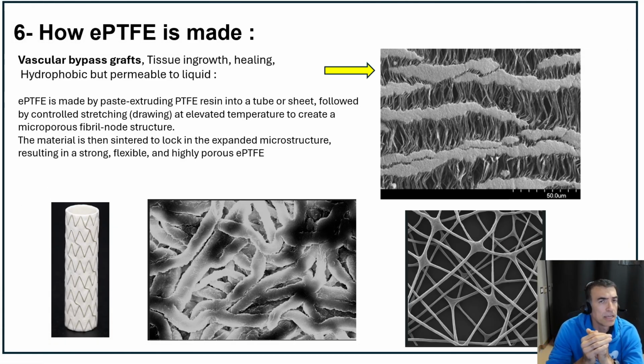We explained that PTFE is sensitive to orientation. It's highly crystalline, and because of that property, when PTFE is stretched, those crystalline structures can create an island shape, and then with further stretching, a structure is formed called fibrillar structure with a crystal lamella in between, and this would create a porous structure that would make the PTFE porous, and that's why it's called ePTFE. So it's expanded PTFE because now you have voids and pores in between these crystal lamellae. And still, because of those fibrillar structures that you have, a crystal-fibril-crystal in the middle, the structure is pretty strong and it will hold the whole shape.